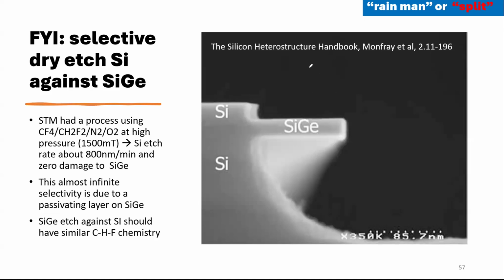If you look at the old book, late 2020, something like that, they have a paper published, a reference paper, that's the other way around. They keep the SiGe and etch the silicon. We're using a CF4, CH2F2, N2, O2 mixture. They configure it, they tweak the knobs of the process, and they come out with etching silicon at like 800 nanometer per minute and 0 to SiGe. See how vertical it is, how rectangular it is. So I think this is infinite selectivity, right?